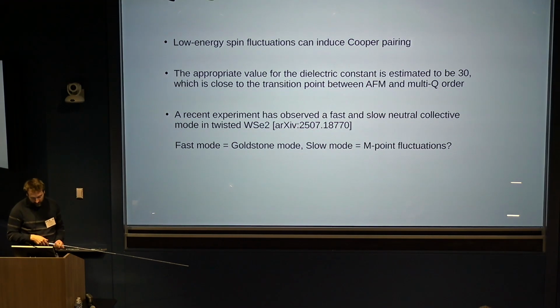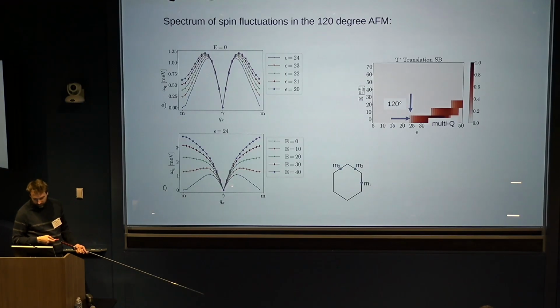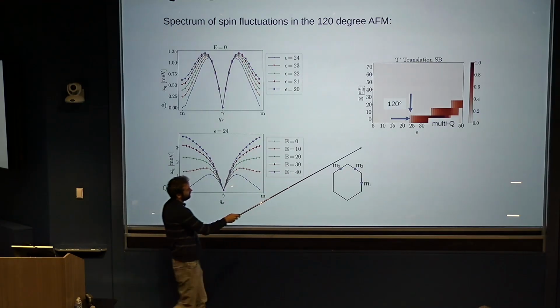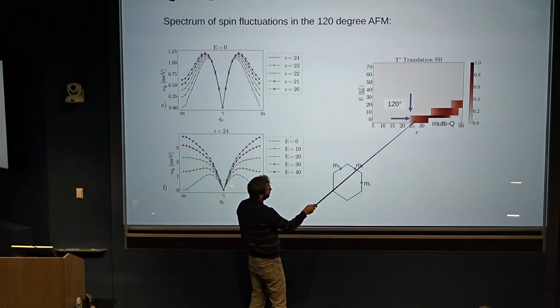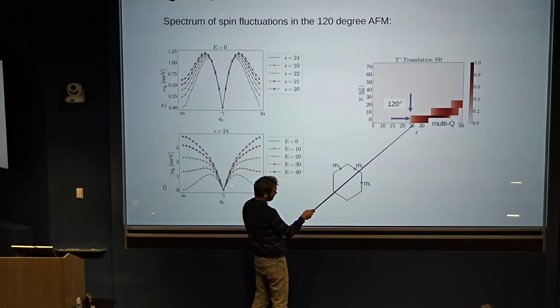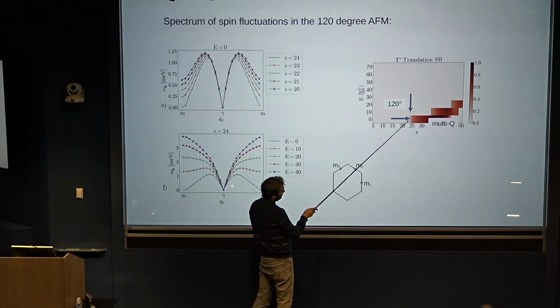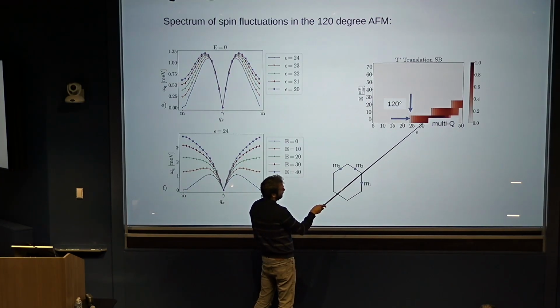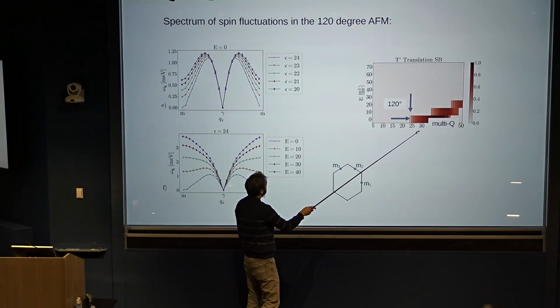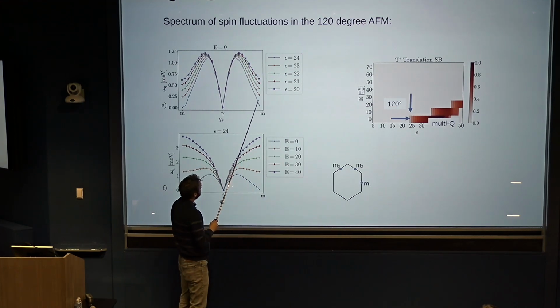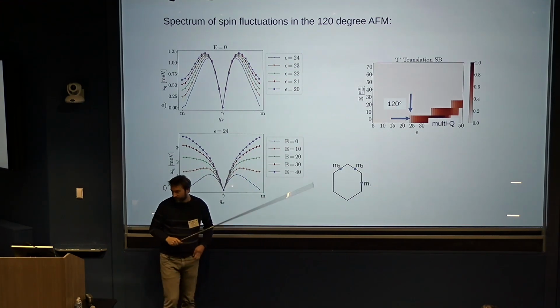And for that value, we're somewhat close to the boundary of this mean field phase transition. Now, given that fluctuations beyond mean field likely push this transition to higher epsilon, it probably pushes it to somewhere here. So I think we're pretty close to where the actual phase transition could be, and so where we could actually have really low energy spin fluctuations at the endpoints.